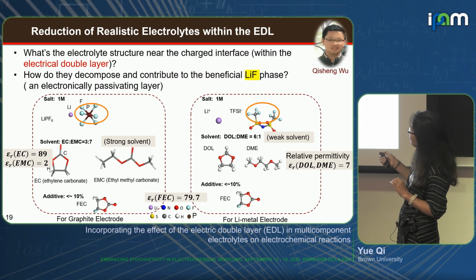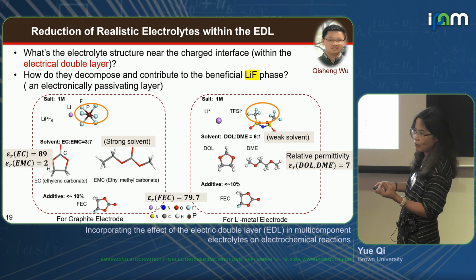And if the ions cannot contribute to the fluorine species, we often add another additive, FEC, fluorinated ethylene carbonate, to contribute fluorine. And so this is the additive. So we look at this with and without the additive.